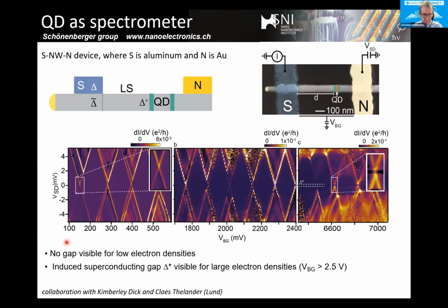So if you go to negative voltages here, it's not shown, then there's pinch off. There are no carriers in the backgate, but from a few hundred millivolts onwards in backgate, the Fermi level will be above the conduction band edge, and you see transport.